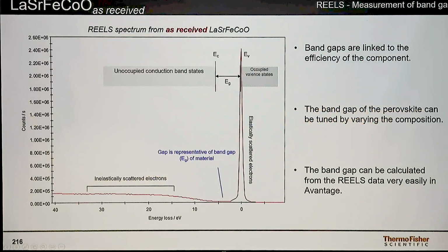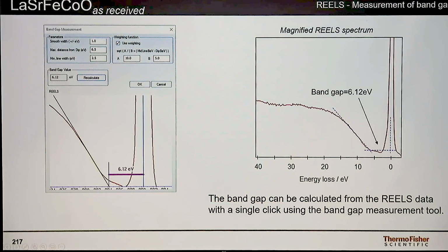And then finally, we can check the band gap. So have a look at the band gap here, and again, just REELS. So you can see the intensity of the elastically scattered peak compared with the background that we're actually using to measure. So this is only about 10% of the scattered electrons, and we're able to measure the band gap in exactly the same way as before. So this is the actual tool in the software for doing it, and once you open it, it just automatically does the calculation and gives you the band gap value for the material, in this case 6.12.